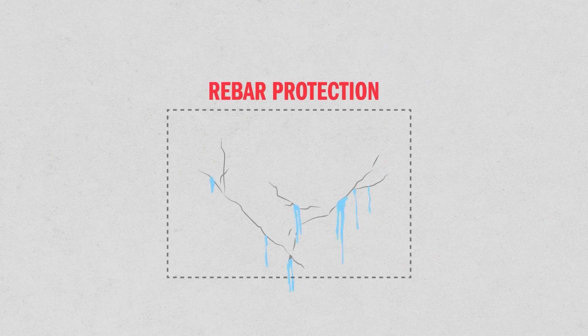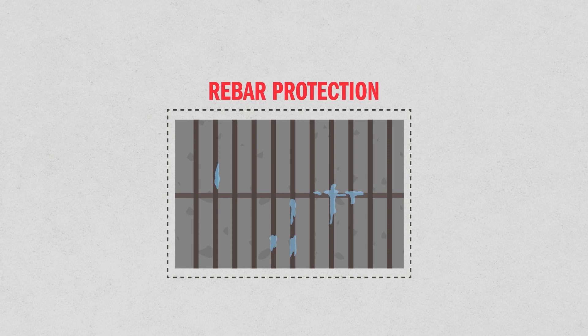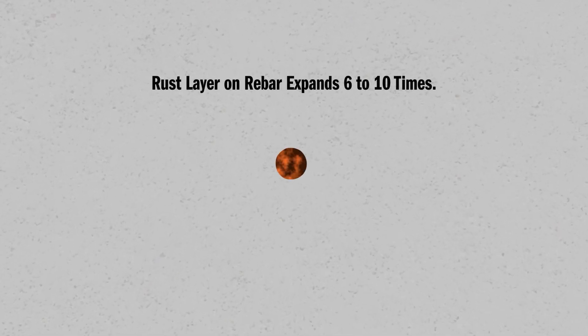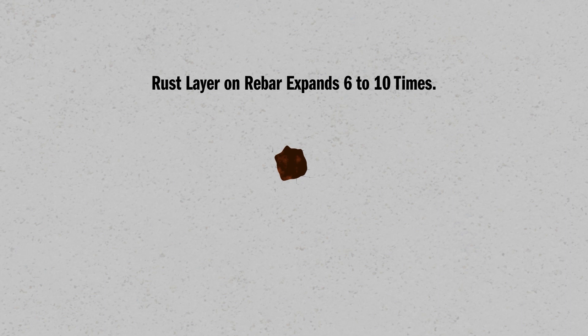Water intrusion through concrete walls with reinforcing steel can lead to corrosion and spalling. Corroding rebar rusts and can expand 6 to 10 times the original volume of the steel. This creates internal pressure on the concrete. While concrete is very strong in compression, it has a low tensile strength and the expanding rebar will cause it to crack.